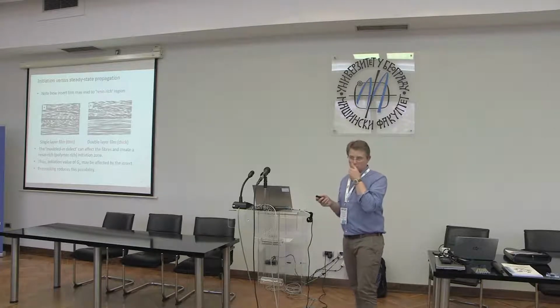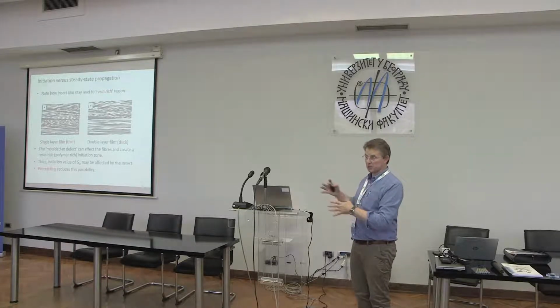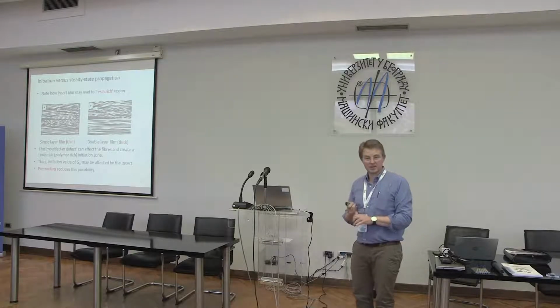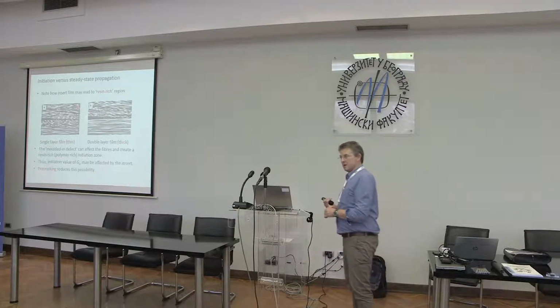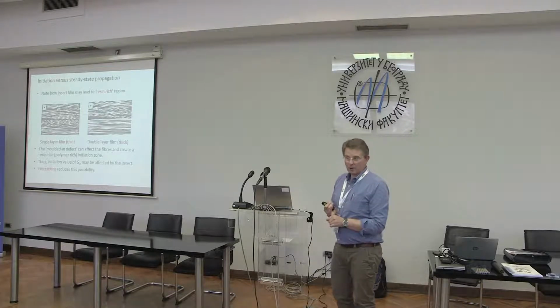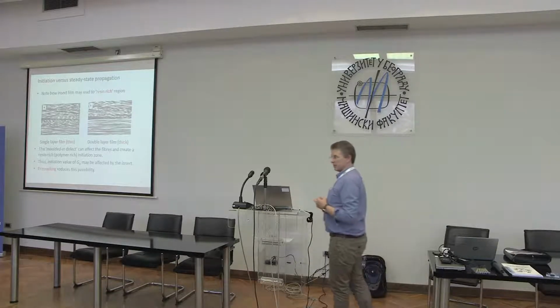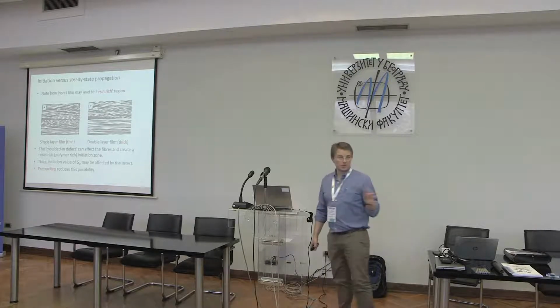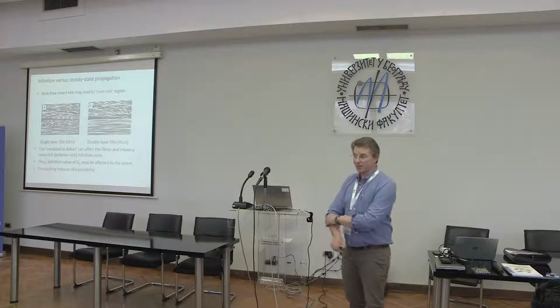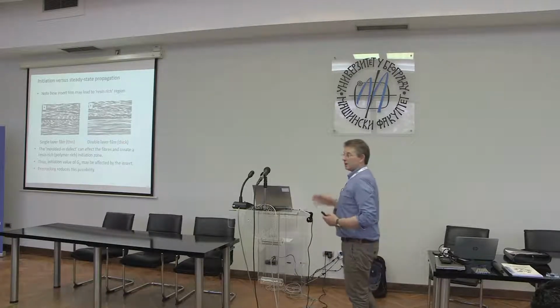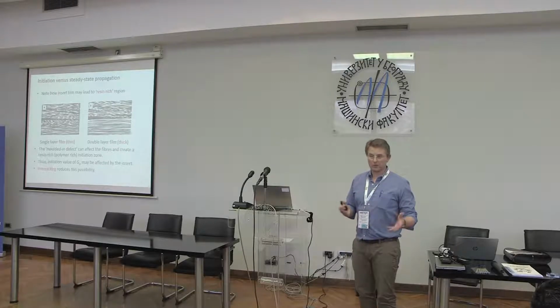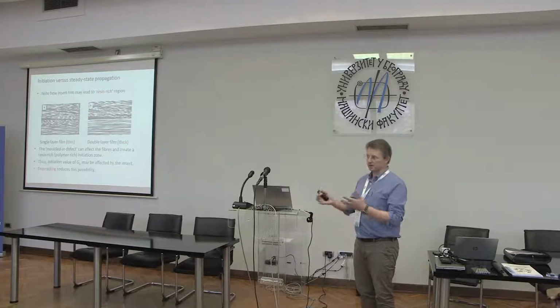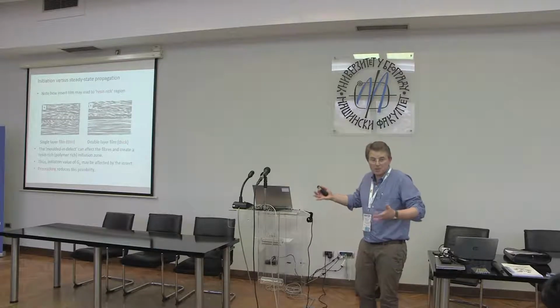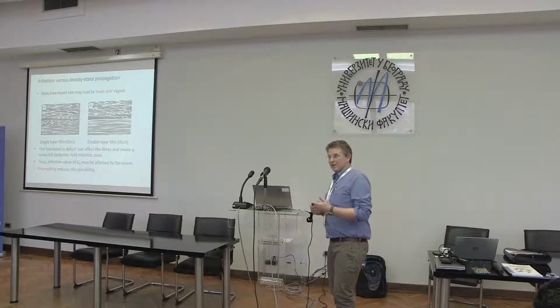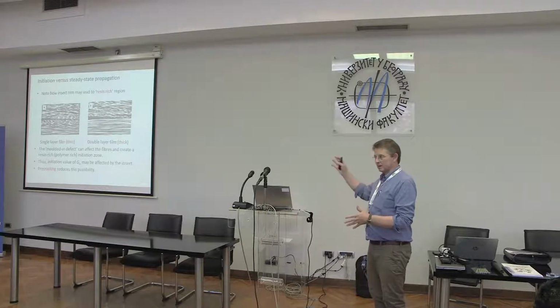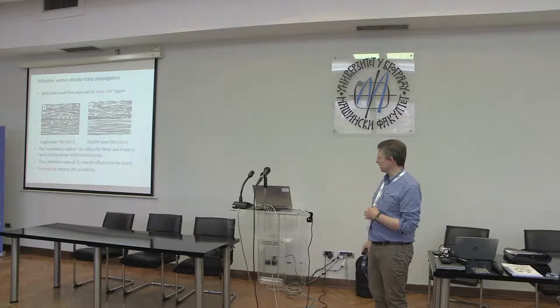So what could be done about this? Well, of course, the very straightforward thing would be to put into the standard a maximum thickness of film that can be accommodated. So don't use an initial film of greater than, and the standard says 13 microns, okay? So of course if you put something into a standard, only a certain proportion of anyone will read it, unfortunately, so you get lots of data out there where people put in 100 micron film. And you see it in research papers all over. You think there's a problem, there's 100 micron film, you know what's happened, okay? They haven't followed the standard, but if you have a thick film in there, you can disrupt these experiments quite badly.